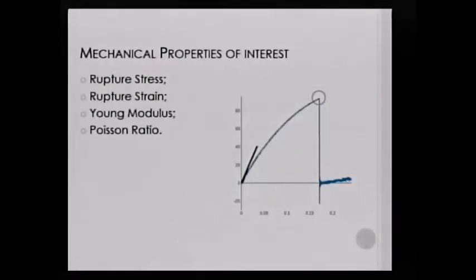And we can see that this is a very different curve than what most of you may have seen in material science courses. You have a brittle behavior that is similar to ceramics, for example. However, you don't have a linear behavior all the way through. This is a behavior very characteristic of carbon nanostructures, and it's very different from what you may find in your average textbook.